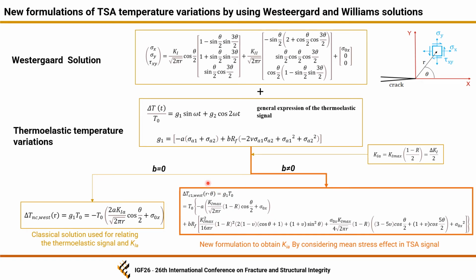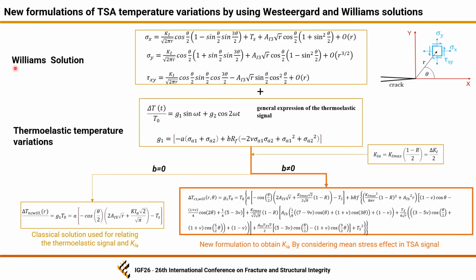And this one is the new formulation, where we can see that the temperature variation depends also on the stress ratio, the material constant B, and the Poisson ratio. In this case, here we have the Williams solution, series expansion truncated to the third term, that is combined with the TSA second order equation to obtain the new formulation.